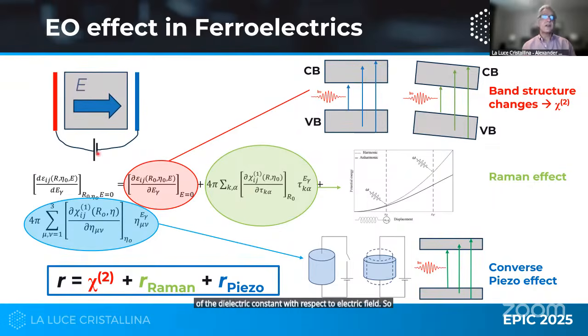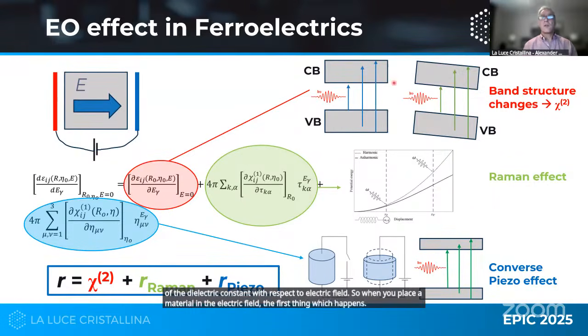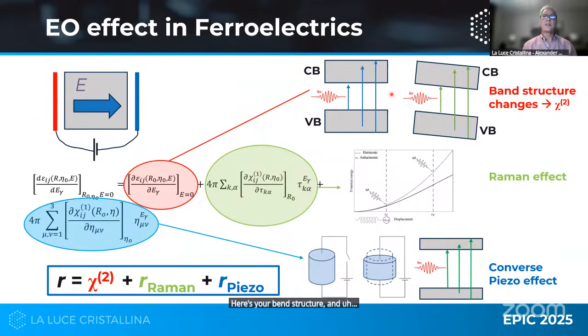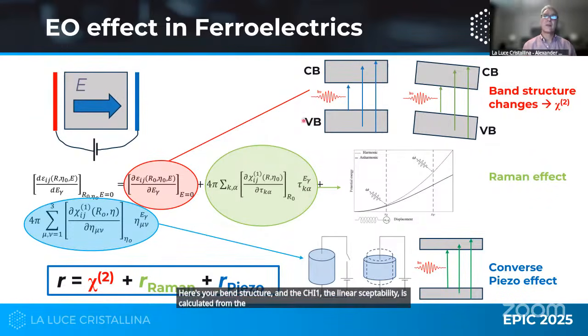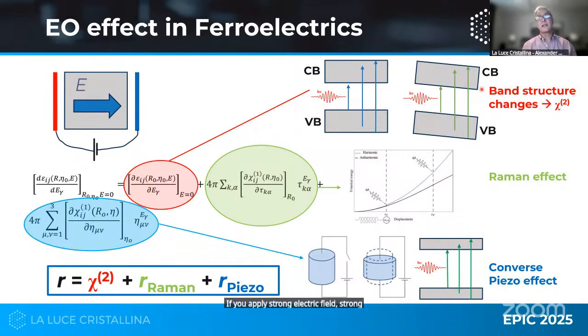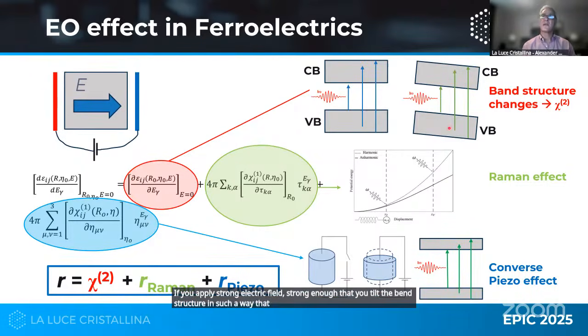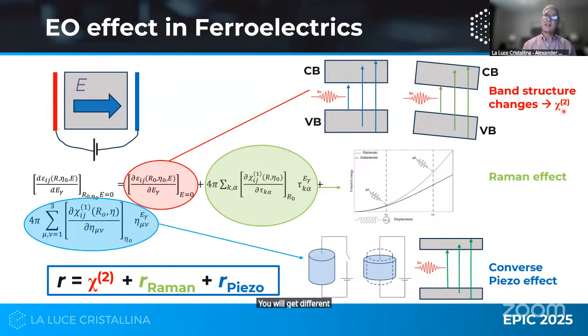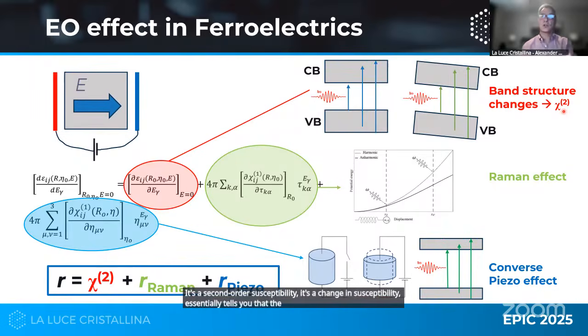So when you place a material in the electric field, the first thing which happens, here's your band structure, and the chi1, the linear susceptibility, is calculated from the transitions from the valence band to the conduction band. So light comes in, you have these transitions, that gives you chi1. If you apply strong electric field, strong enough that you tilt the band structure in such a way that these transitions are all different, you will get different susceptibility, and that's described by chi2. It's a second order susceptibility. It's a change in susceptibility, essentially tells you that the dipole is not proportional to the field, it's proportional to the square of the field. So that's the main effect in a material like gallium nitride or indium phosphide. It's a very fast effect because it requires electrons.